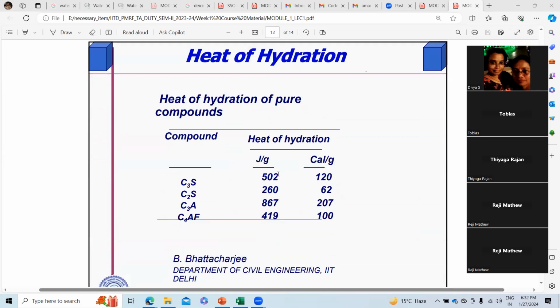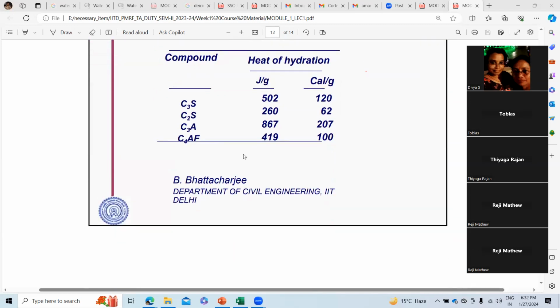Now the heat of hydration. See, this is the heat of hydration. You can check C3S, C2S, C3A and C4AF. Of all, the maximum is C3A. C3A reacts quickly with water, and I can show you later how it reacts. C3S gives the initial strength of the cement, and C2S gives the ultimate and long-term strength. C3A does not give much strength, but its heat of hydration is much more.